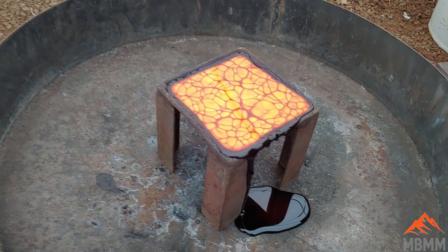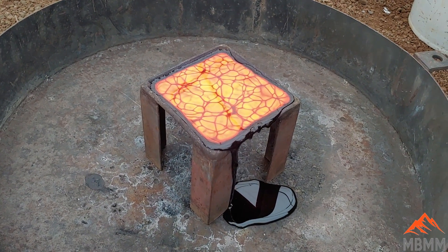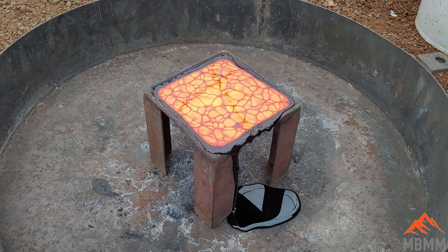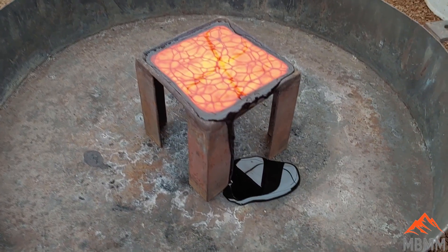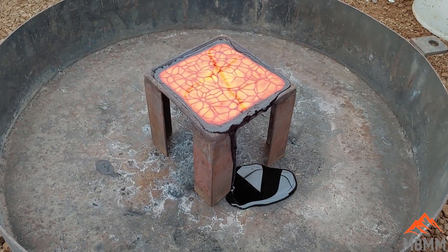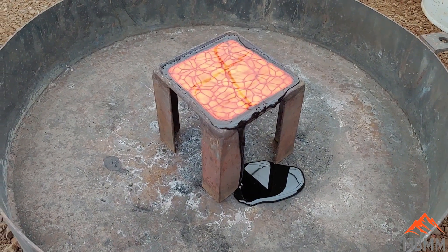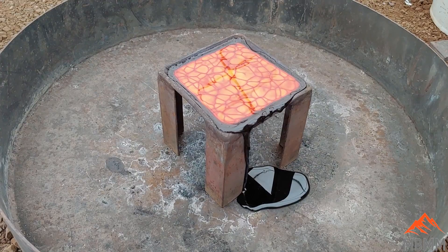Get that respirator off — and there's our pour. Poured pretty nice. The slag was a little bit thicker than I would have liked. I think there's a little bit of silica in the material, so it may have thickened it up a little bit, but it looks nice and glassy. Even if I get a little bit running over, all the lead and the gold is so dense that it just goes right down to the bottom of the cone mold — none of it flows out into the slag that runs over the edge. So we'll let that cool down and take a look at our collector metal button at the bottom.